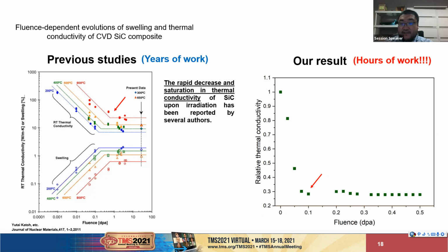In our work, as you can see in the red figure, this is the first time we got the relative thermal conductivity of the silicon carbide composite as a function of ion radiation. We got a similar trend, in agreement with the previous study, but the time we used is only 5 hours. So you see how efficient this innovative technique is to get the result.